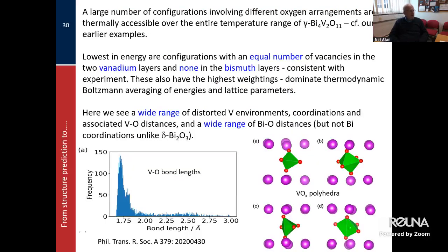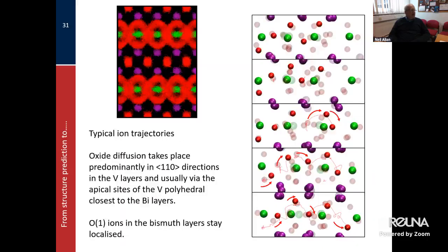We looked at a lot of possible local arrangements, both by doing minimizations of possible structures. And there, that started to indicate that I was going to be wrong, because first of all, we found that basically oxygen vacancies were not going to be in the bismuth layers, but in the layers where there were vanadiums. So that started indicating that actually the vanadium oxygen layers were very distorted. And indeed, what we saw was that the conduction didn't involve the bismuth layers at all.